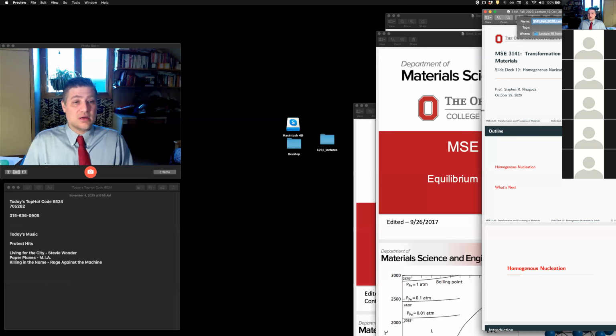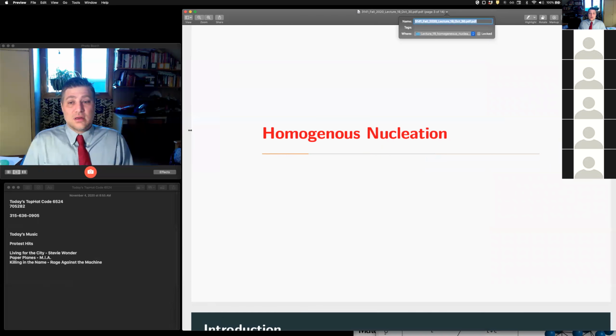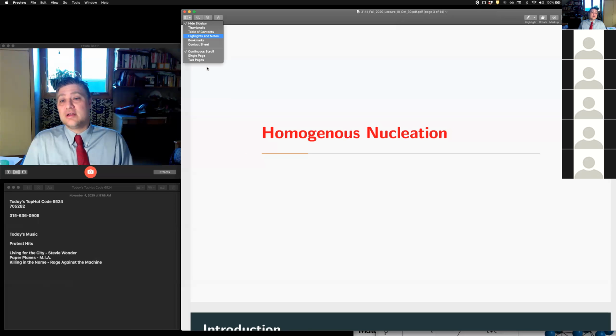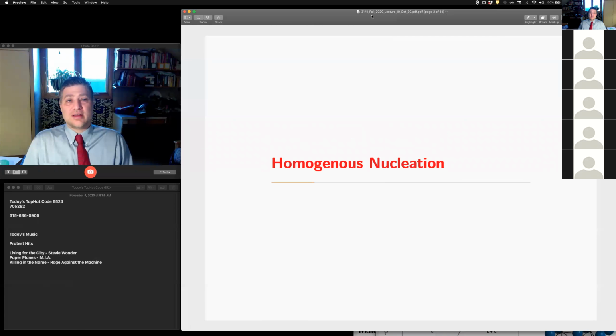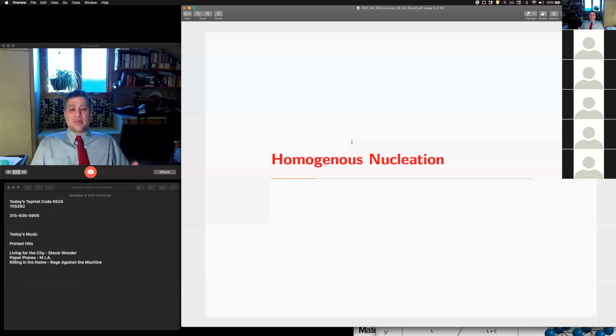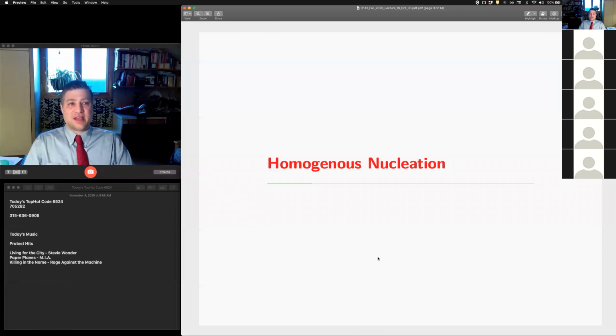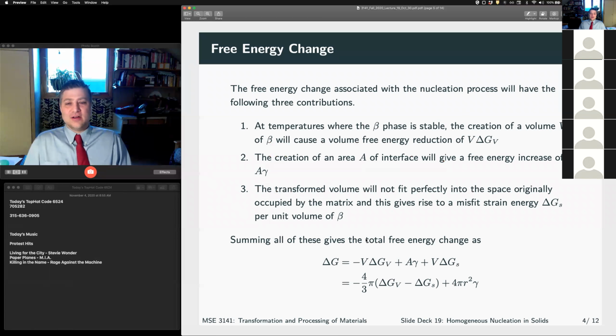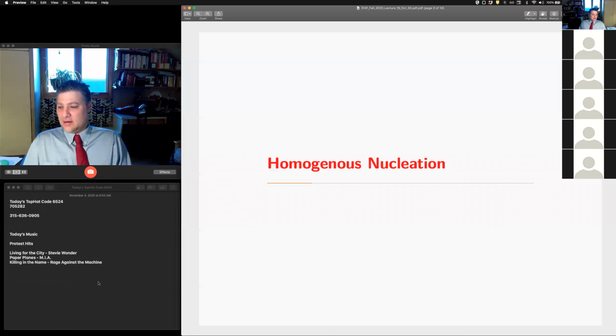Okay, so we were talking about homogeneous nucleation, right? And the important thing to remember is that this is exactly the same as solidification for the most part. Have we gone back in time to homogeneous solidification or something? It is. This is it. Nucleation in solids is exactly the same as solidification, right? As nucleating solid from liquid.